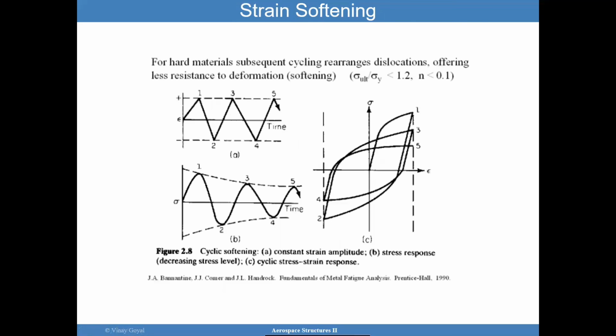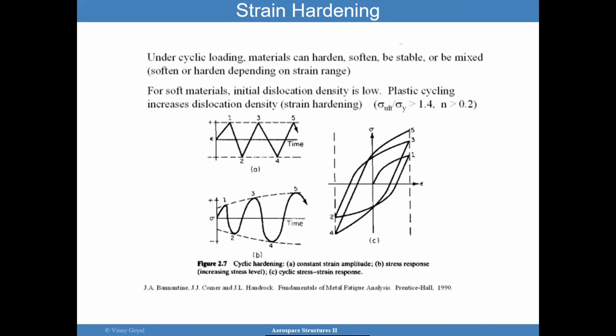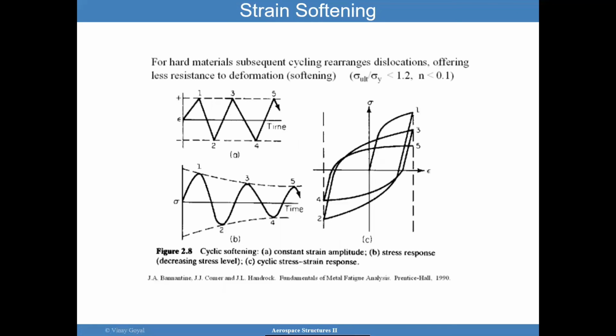For hard materials, cycling can rearrange dislocation. So these for soft materials, these for hard materials. And it offers less resistance to deformation. In these scenarios, you may see a situation where for constant strain amplitude, the stress decreases. And you can see that here as well, the stress is decreasing over time. We call this cyclic softening.